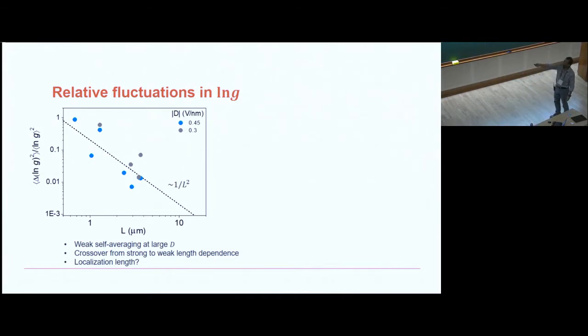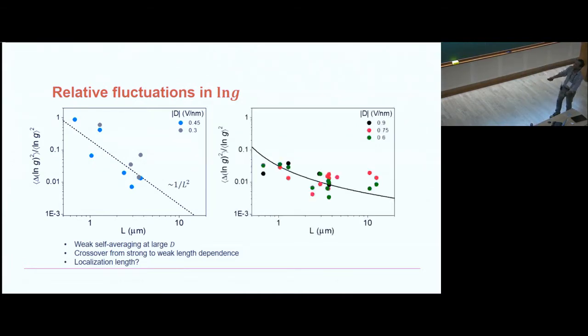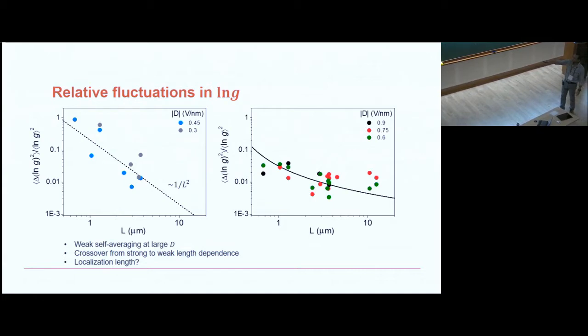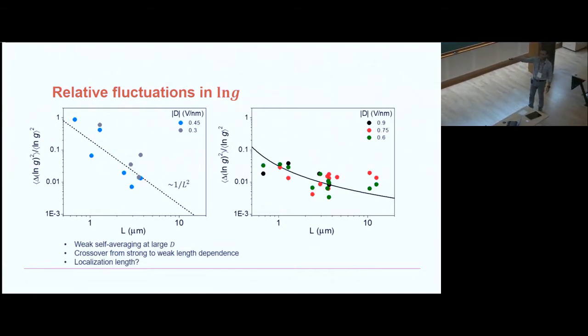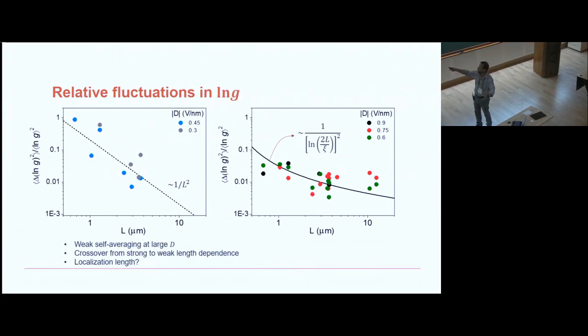However, if I make this band gap large by applying a large electric field, now I can see that as you increase the length, this parameter doesn't decrease at all, almost nothing at all. This is, of course, a statistical experiment, so there would be a lot of noise, but it's very easy to see that the sharp dependence at low values of D is absent in the case of large values of the band gap. That means essentially we have a 1-dimensional transport. This is 1 over log G with the experimental error.